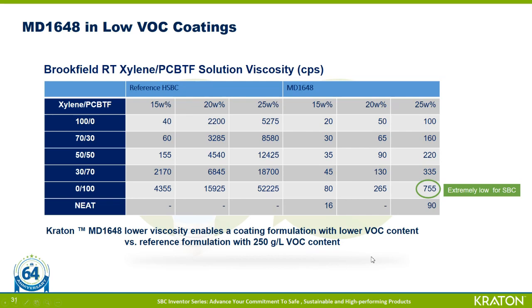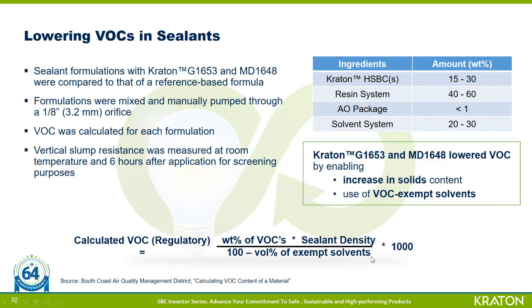In this study, we illustrated improvements in VOC reduction by utilizing Kraton G1653 and MD1648 and comparing to another HSBC-based formula. So we made basic sealant formulations that contained Kraton HSBCs, tackifying resins, AO, and a solvent system in the table on the right. We then calculated VOC content for each formulation, and we did that just by utilizing a basic formula that's readily available online. In this case, we received the formula from the South Coast Air Quality Management District, as shown here. And we then measured vertical slump resistance at room temperature just for screening purposes.